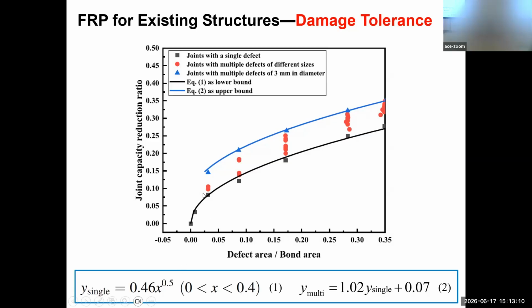So we did some curve fitting. For the lower boundary, this is the simple formula. For the upper boundary, you calculate the lower bound, then add a 7% additional reduction on top of the single defect reduction factor.